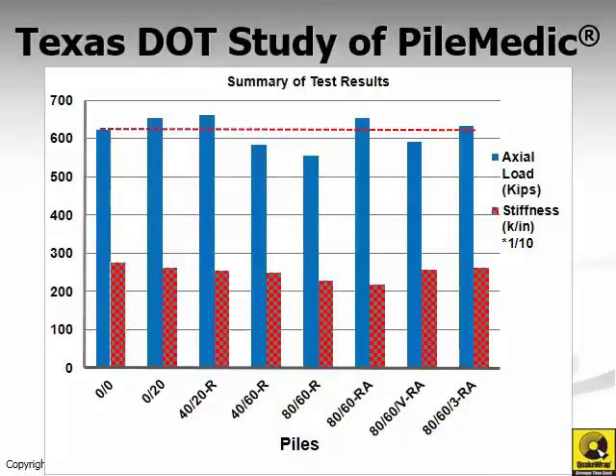The letters R, for example, indicate that just rebar was added, and RA indicates that rebar plus a headed anchor was added. But the main point is that the original undamaged column had a load capacity around 620 kip, and several of the damaged and repaired columns even exceeded the capacity of that undamaged column, as shown by going beyond the red line in the graph. And in the remaining two or three cases, the capacity of the column was virtually restored as a result of this repair, although it did not exceed the undamaged column capacity.